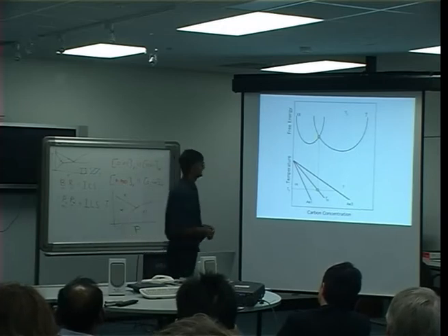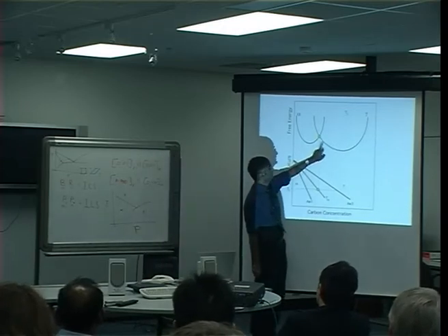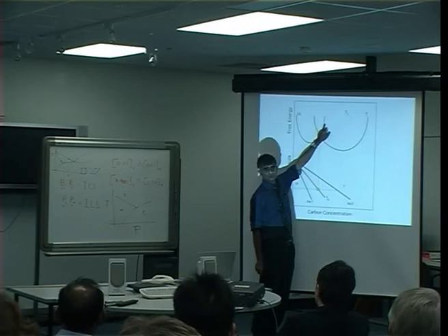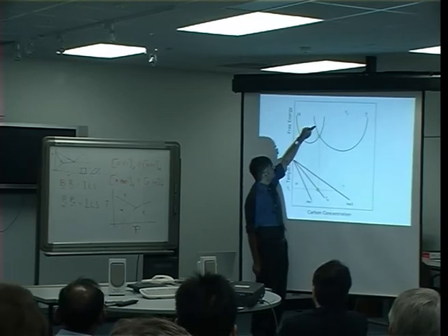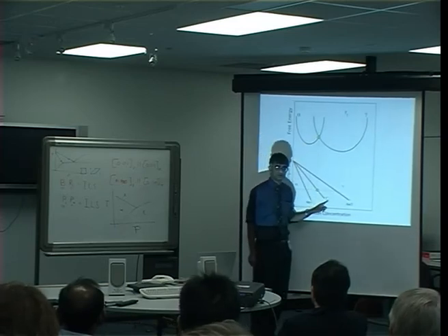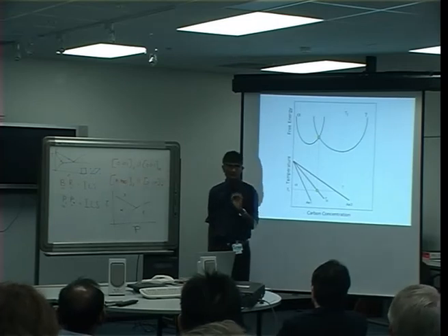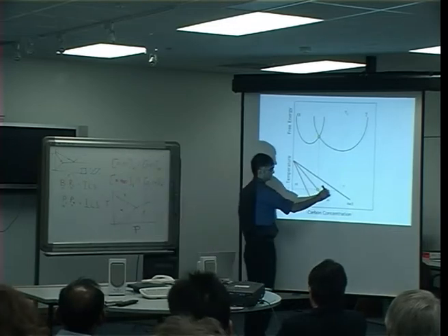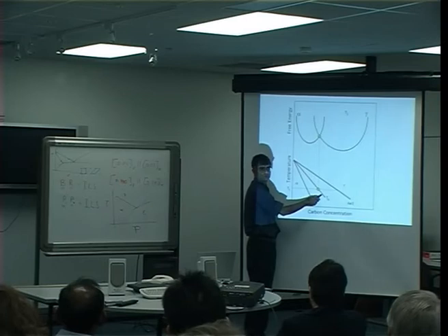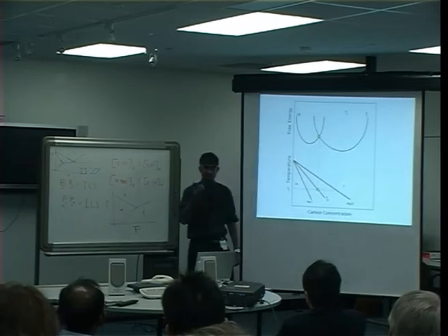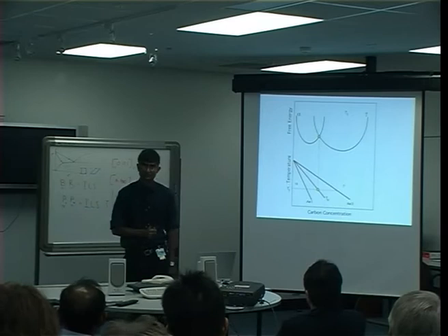And the importance of this curve is that if austenite is of this composition, that means richer than this point in carbon, then it's impossible for it to transform without diffusion, because that will lead to an increase in free energy. On the other hand, on this side, even if I don't change chemical composition, I have a decrease in free energy. So this defines the limit beyond which it is thermodynamically impossible to get martensitic transformation. You know, if I have austenite of this composition, it simply cannot transform by a diffusionless mechanism. Okay, so this curve is really quite important and sets the thermodynamic limit to diffusionless transformation.